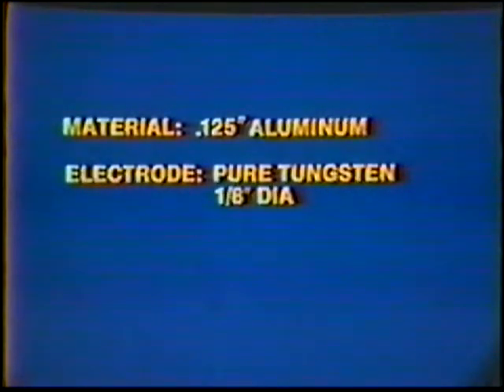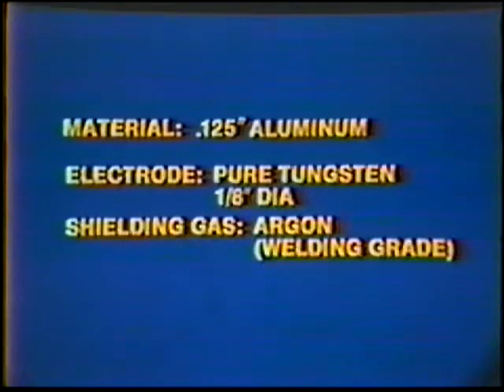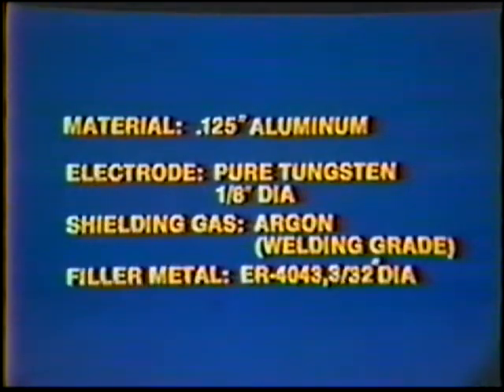Material. For the remaining job practices, we will be working with 125 thousandths inch aluminum plate. The pure tungsten electrode is used with alternating current. The shielding gas remains welding grade argon. The filler metal will be ER4043 and should be 3/32 inch in diameter.